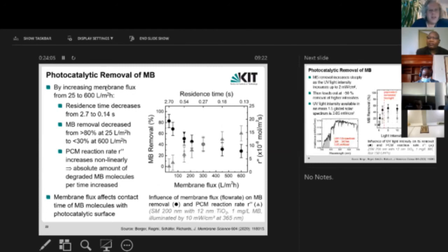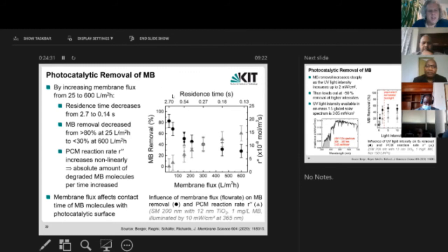Then we look at just taking that one membrane and increasing the membrane flux. This is the flow rate through our system. And you can see by increasing the flux up to 600 liters per meter squared per hour, you can achieve residence times, shown on the top x-axis, of somewhere in the range of 0.1 to a handful of seconds. These are relatively fast residence times for photochemical reactions. Here we're showing that you can get up to about 80% removal at the lowest flow rates, dropping down to about 30% at higher flow rates.